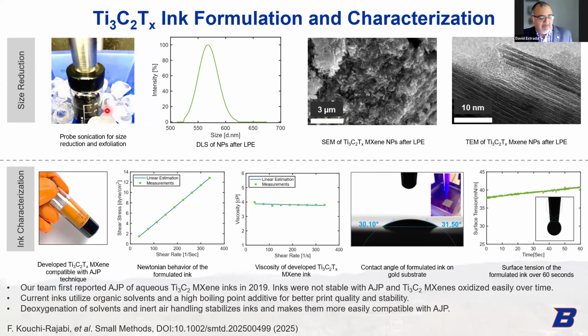What we've done is we follow some of the work from Josh Wood and Mark Hersam, where we actually do our synthesis using deoxygenated solvents, and we seal everything in an argon glove box before we do probe tip sonication to reduce the particle size. Here, we have our solution in ice, but this probe tip is actually a PDMS system that will seal under argon, and then we take it out and connect it to the probe tip sonicator to do the particle size reduction. We measure that with DLS. You can see we're down in that 500 nanometer range, 500, 600, which works well for aerosol jet.